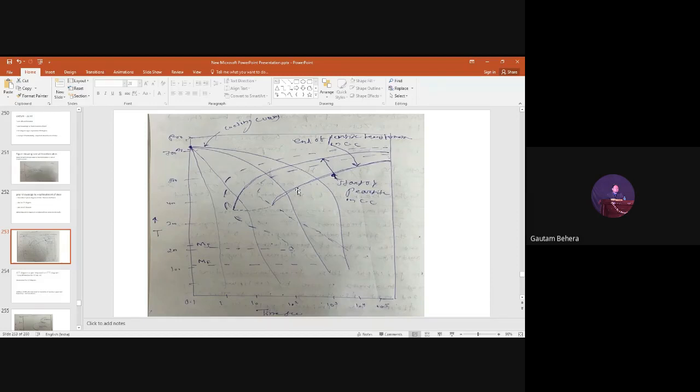You are getting my point. The sample temperature will change slowly. The sample temperature from 800 degrees centigrade to room temperature, for example, 25 degrees centigrade, will cool very slowly. It will take some time to reach 25 degrees centigrade from 800 degrees centigrade. But if you are using a salt bath furnace and you are doing very rapid quenching, it will not take much time. Suddenly from 800 degrees centigrade, within a fraction of a second, it will reach 300 degrees centigrade. You understand my point?